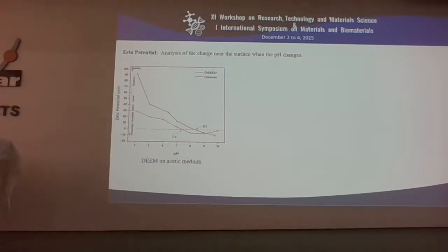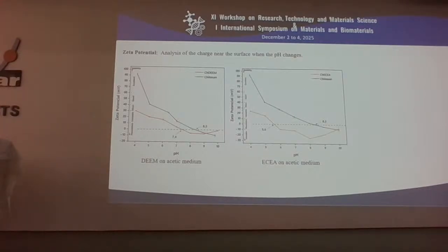So I did zeta potential to analyze the charge near the surface when I change the pH, just to understand if the absorption will be affected by the change of the pH in my modified chitosan. As you can see, and as the Professor said, when we have lower pH, I'm using acetic medium, we have a higher stability on chitosan. But my derivative has an unstable suspension. For the second one, it's the same thing. In acetic medium, of course, it is unstable at the lower pH.